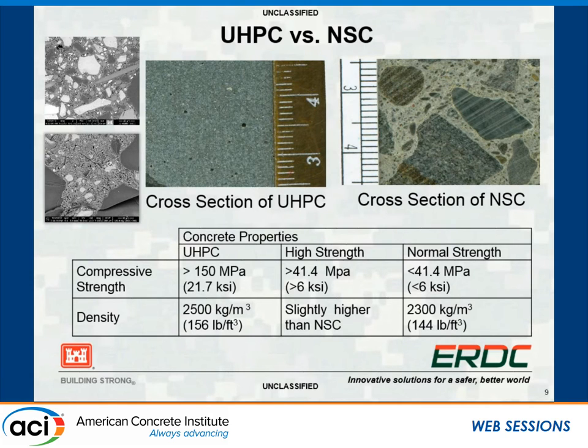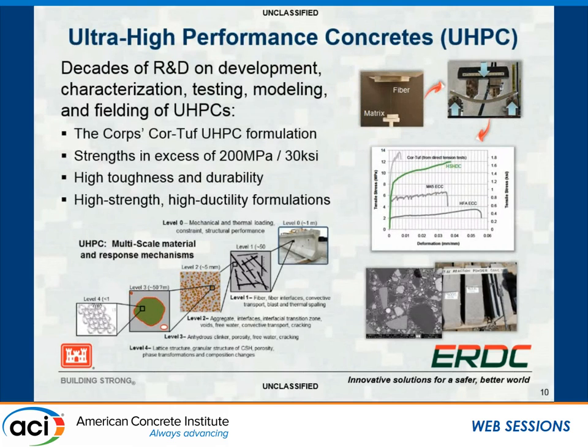You can see the differences in compressive strength and densities. UHPC is a little bit higher in density, and we do incorporate steel fibers in a lot of our products, which gives a kick in density due to the fiber loading—generally more than what the manufacturer recommends, with some of ours approaching about three times the recommended amount. We use construction-grade fibers in some materials. Higher-density aggregates could be added to increase density further. The biggest visual difference in most UHPCs is how small the grain sizes are compared to the coarse aggregate in conventional concrete.